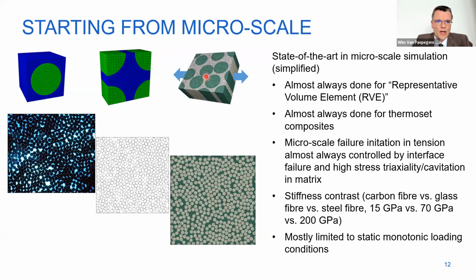But then you move on and have a random packing of fibers. Here you see again the periodic nature. So the fibers are assembled left and right. You can get a full fiber again. But more realistically, you generate a random packing, which looks like a real microstructure. And again, you apply the periodic boundary conditions.